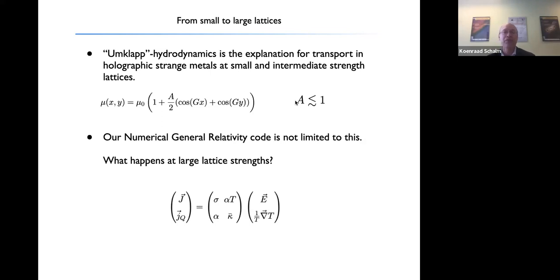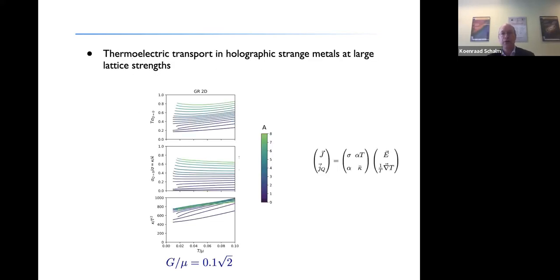So we can simply now ask an explorative question: what happens at large lattice strength? What happens to the thermoelectric transport in such a holographic strange metal if I could make the lattice very, very strong? Well, this is what happens. What you see is that the resistivity becomes, if at all possible, ever more linear in this system. This is the answer for the conductivity.